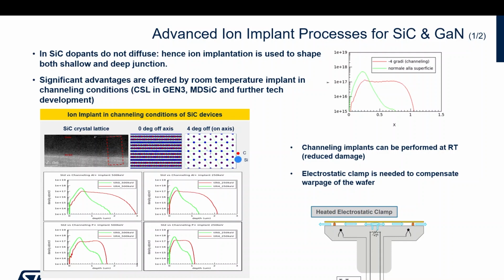So instead of implanting in a random direction, you implant through the axis of the device. Compared to random, which is the green, channeled ion implantation, which is true also in silicon, by the way, but in silicon carbide is even more important, can go much deeper and with a distribution which is more flat. So ion implantation in channeling condition is a very important technology for silicon carbide. It will be used more and more in the near future.